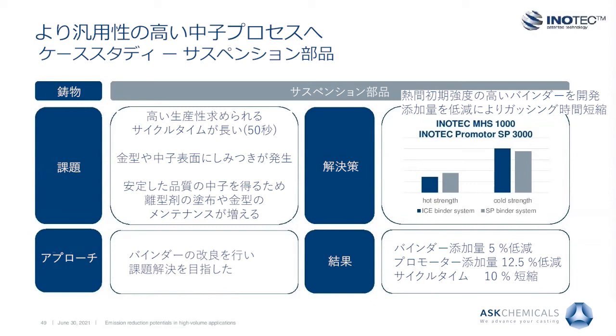The second example arises from the field of suspension part castings. The customer reported a limitation in productivity due to long cycle times and reduced tool availability in the core shop. The current addition rate of the inorganic binder system was in principle too high, but necessary to handle voluminous cores because of strength. The buildup of binder system residues on the core box surface and the core itself resulted in an excessive use of release agent and tool maintenance work in short intervals.